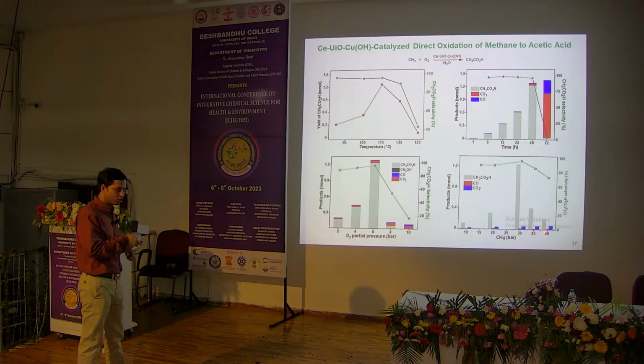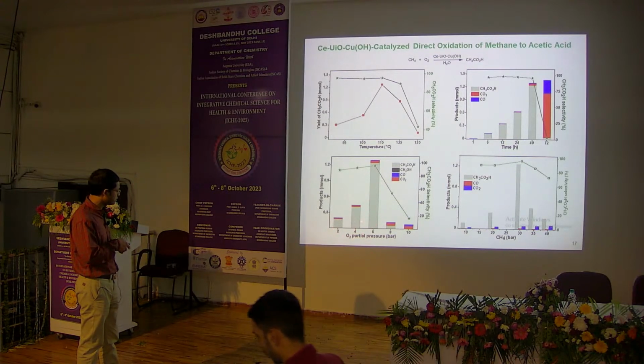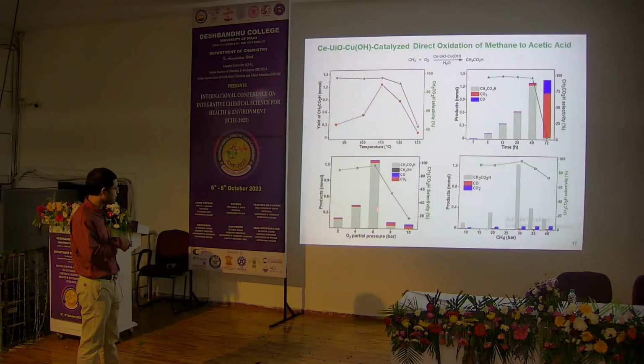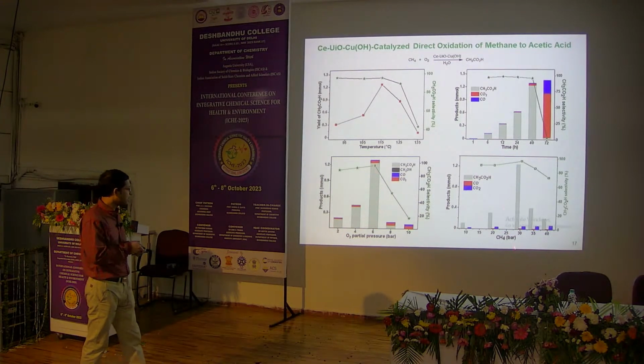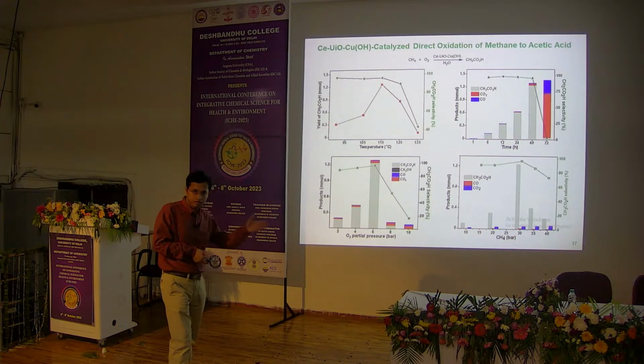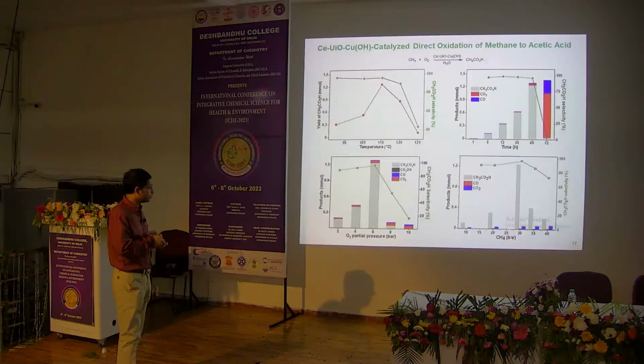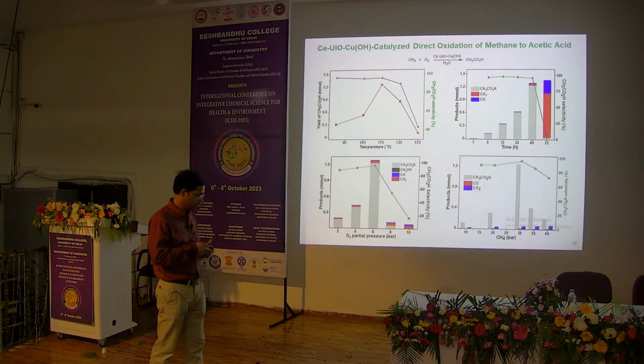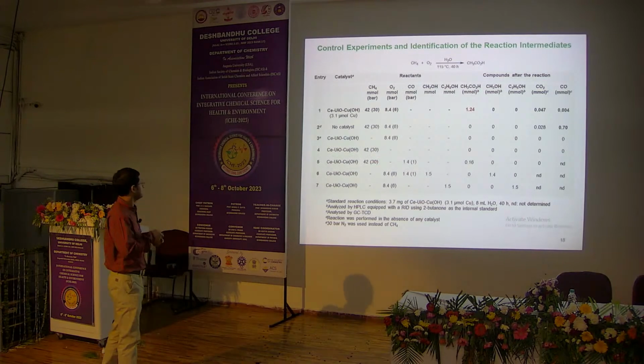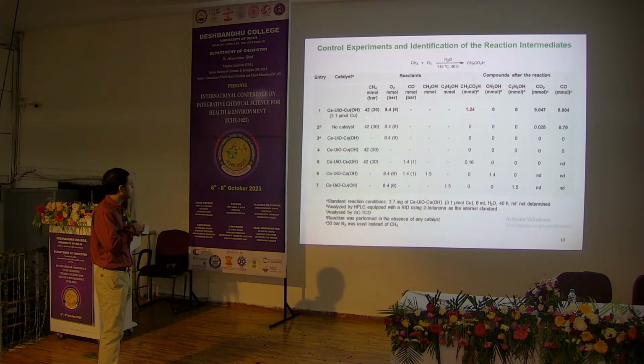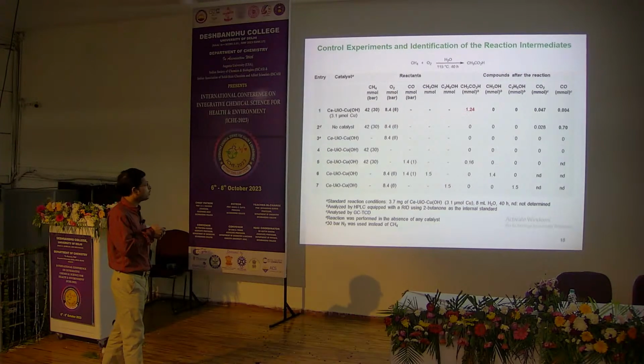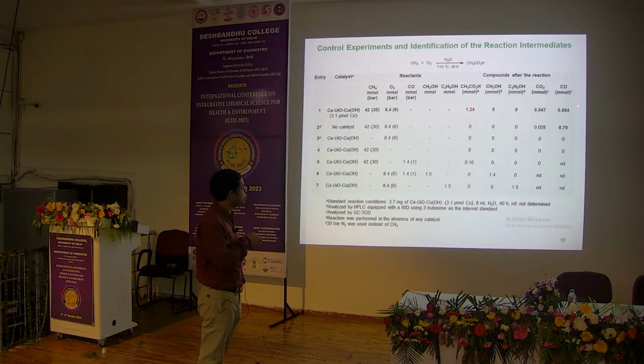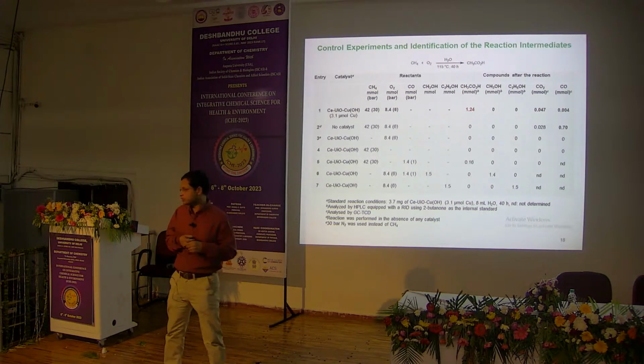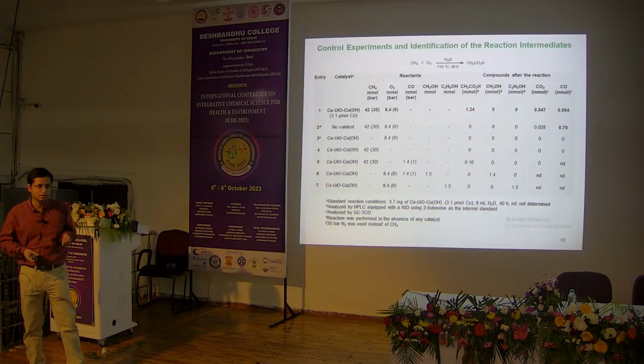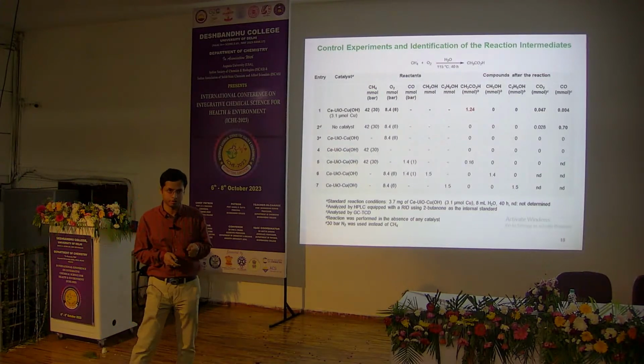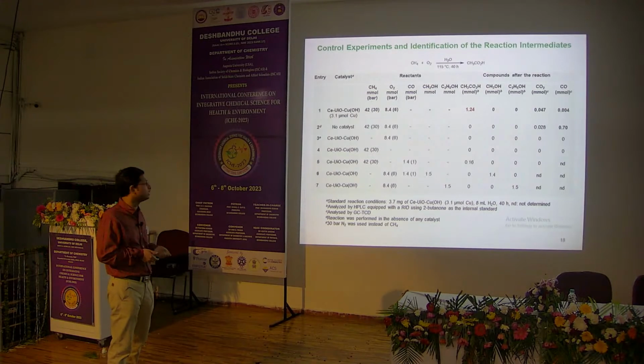Oxygen pressure and methane pressure are also important. The yield of acetic acid depends on the oxygen pressure. At 6 bar of oxygen we get the highest acetic acid yield, and it also depends on the methane pressure. I will explain later why. At 30 bar of methane we also got the highest amount of acetic acid. In the optimized conditions, we started with methane at 30 bar, that is 42 millimole of methane, and oxygen at 6 bar, and we got acetic acid 1.24 millimole with a negligible amount of carbon dioxide and CO. That translates into 6% conversion and more than 98% selectivity. That is the highest selectivity among any other catalyst reported in the literature.